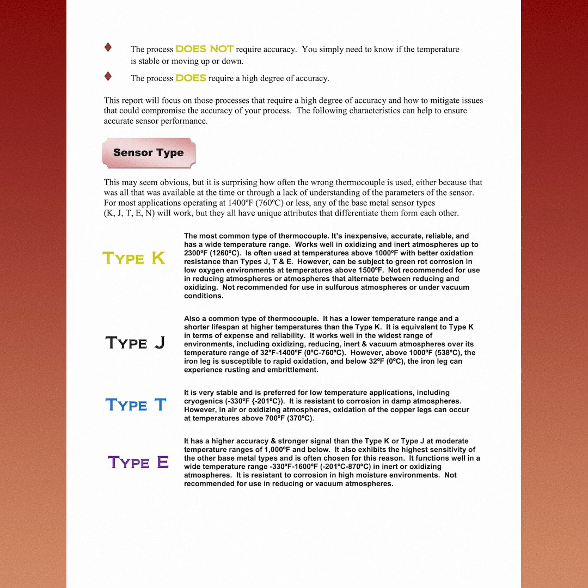Type T, very stable and preferred for low-temperature applications, including cryogenics, minus 330 degrees Fahrenheit or minus 201 degrees Celsius. It is resistant to corrosion in damp atmospheres. However, in air or oxidizing atmospheres, oxidation of the copper legs can occur at temperatures above 700 degrees Fahrenheit or 370 degrees Celsius.